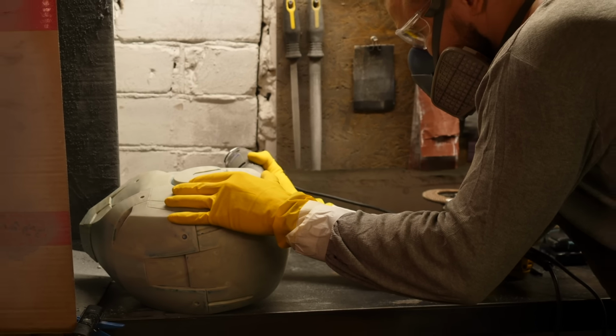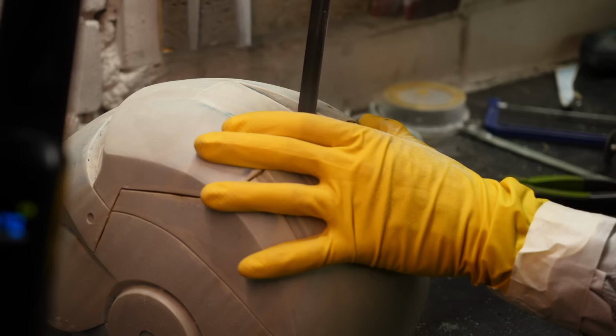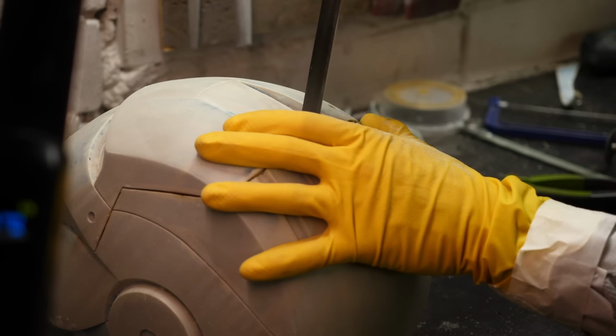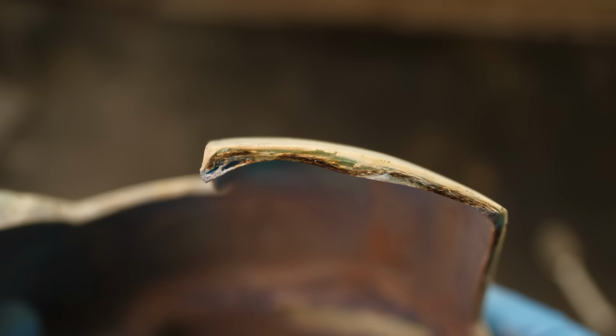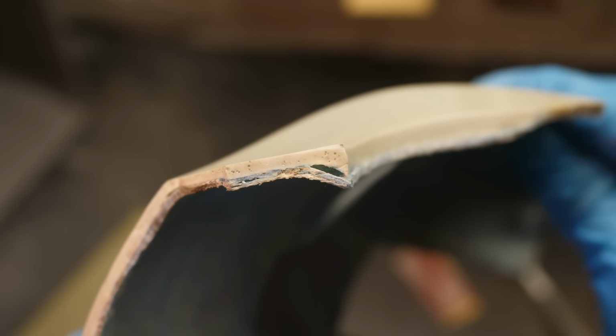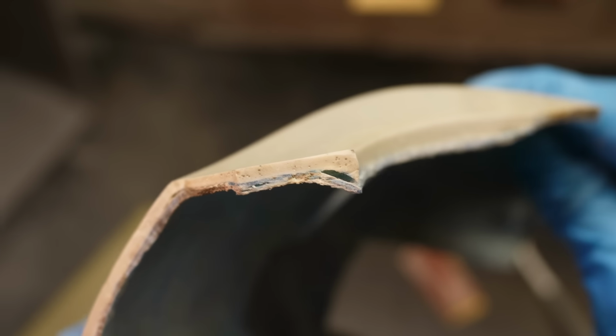In the later models, once I got the hang of achieving a dense laminate even in complex corners and recesses, this problem didn't occur anymore. But in the early versions, after cutting, it was noticeable that the lamination hadn't settled properly in the corners. Such issues are fixed using a DIY UV curing putty. We take resin for SLA printing and add some baby powder to it until a thick paste forms.